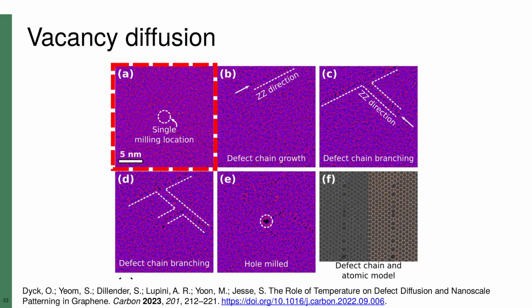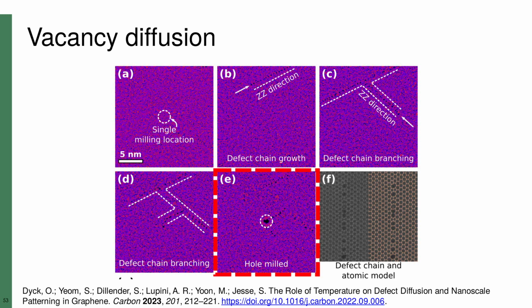Here we decided to mill just one hole at the center of the image, but periodically during the milling process we acquired a full image frame to see what happens to the adjacent areas of the graphene during this process. What we found is that chains of defects grow into the imaged area and branch toward the milling location. When they finally grow into the milling location, then we are able to form a hole.